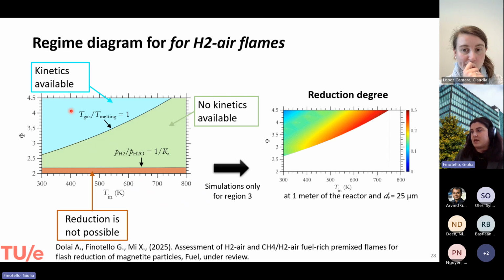It means that we decided to simulate only this part, and with this model, we could really predict what the reduction degree was, simulating again this region 3. It is this region on the top, with inlet temperature and equivalence ratio. You can see that you can reach a higher reduction degree, of course, at higher temperature and higher equivalence ratio.